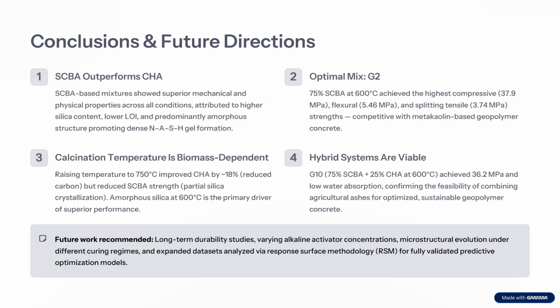To conclude, for the best value we have to balance between the amount of silica and the amount of fuel carbon. We can say the highest value can be achieved when we add 75% SCBA plus 25% of the CHA at 600 centigrade, with a compressive strength of 36.2 megapascal.